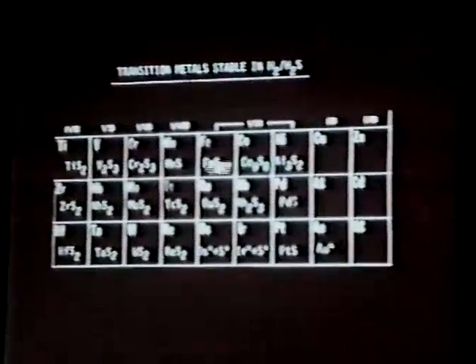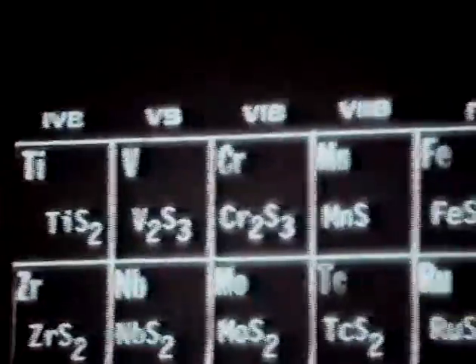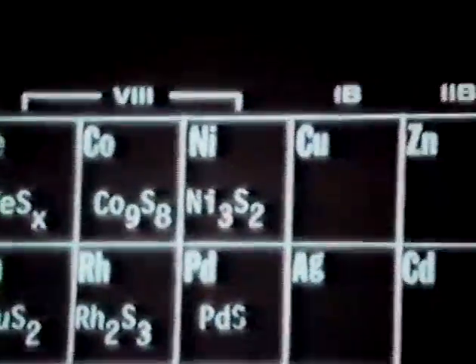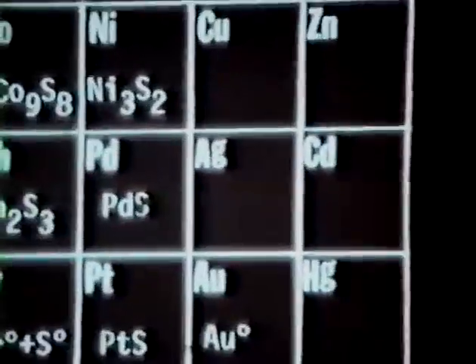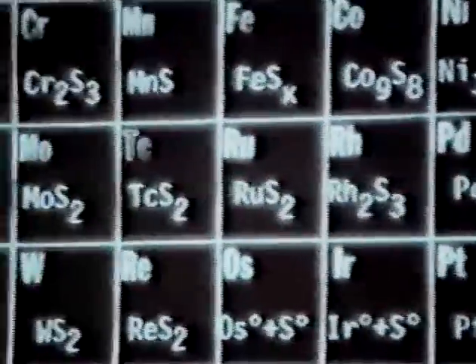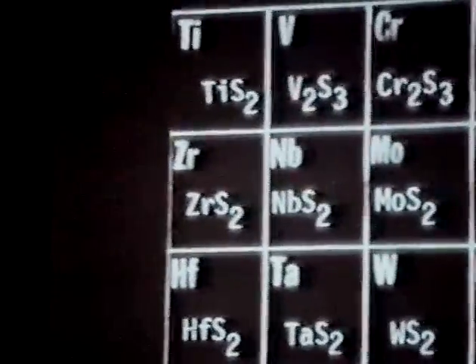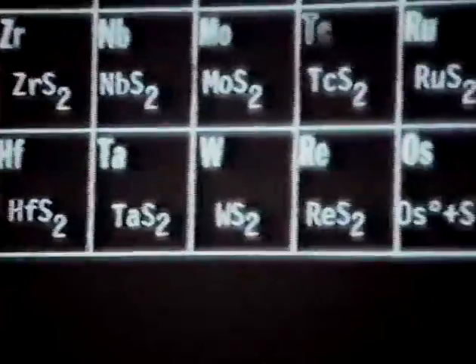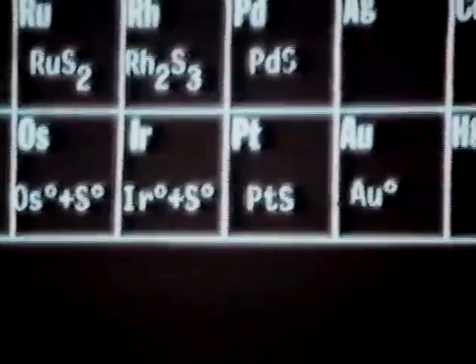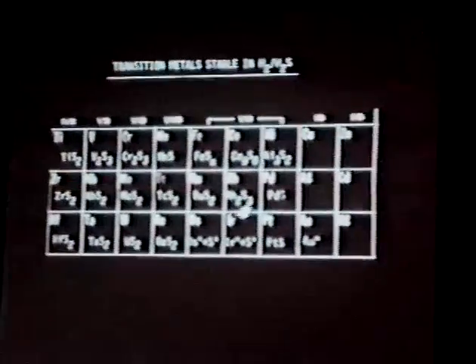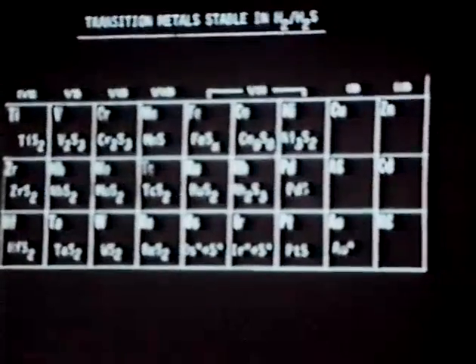To start off again, these are the stable states - the materials that come out of the reactor under those conditions, identified by X-ray diffraction. I think it's another important principle, as I said earlier, to identify those stable states. So all of these catalysts were made and run in the reactor under the conditions that I showed you previously. The catalysts are taken out of the reactor and identified by X-ray diffraction and other methods. Now what I would like to point out about this particular set of structures is that they're all quite different - most of these are layered sulfides, like molybdenum sulfide, which I'll speak a bit about later. But ruthenium sulfide is a pyrite structure, and rhodium sulfide has a very different three-dimensional structure. This was a surprise to us - that when running these under reactive conditions and identifying the stable states, the structure was varying quite a bit.